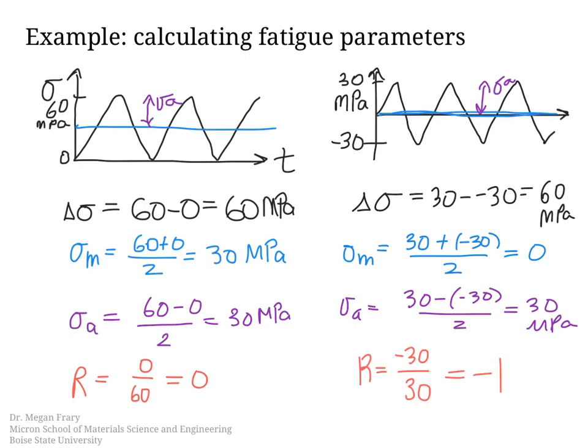And let's just finish now by finding the value for the stress ratio. So in this case, we find a stress ratio equal to negative 1, and a stress ratio equal to negative 1 will actually always be the case when we have the same amount of stress in tension as we do in compression. So that's what a value r equals negative 1 corresponds to.